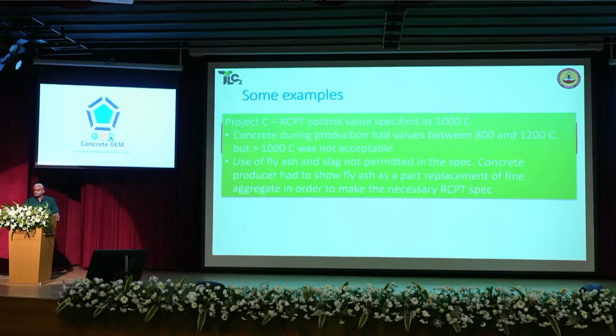So in this case, of course, the contractor came up with an interesting solution. They said, okay, we'll not use fly ash as a replacement of cement. We'll show it as a replacement of sand. So they had fly ash in the mix. Ultimately, they got the concrete to show an RCPT value of less than 1,000. So again, it's not cheating, but what you have done is essentially not reduce the cement, but increase the cementitious content by showing the fly ash as a partial replacement for the fine aggregate.